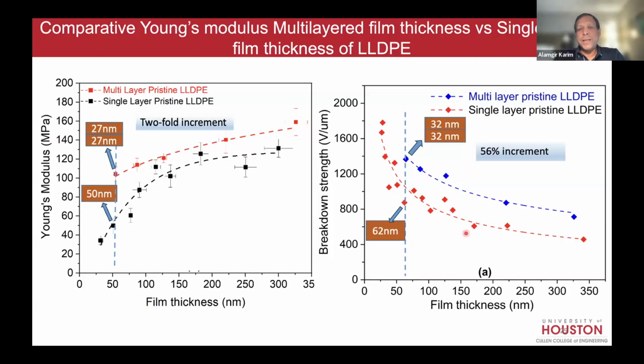So already we do that, and there's this extrusion technique that 3M uses to make these multi-layered, multicolored iridescent films. That was a Dow technology, and they make films in this thickness, 30, 40 nanometers. 3M already has the technology. For example, it's a commercial technique that was developed, I was at NIST, and Daryl Reneker is the person who actually developed that technique when he was at DuPont. Okay, so the machine exists. You can make sheets and sheets of 40, 50 nanometer easily currently.